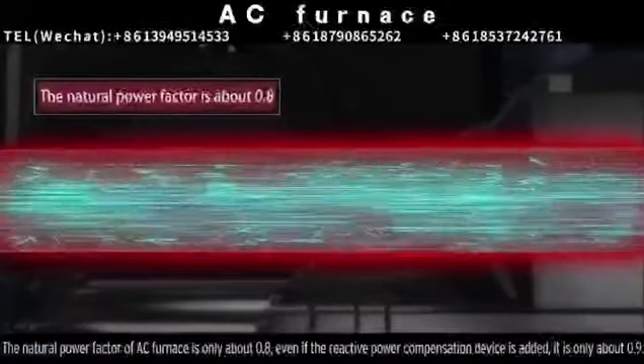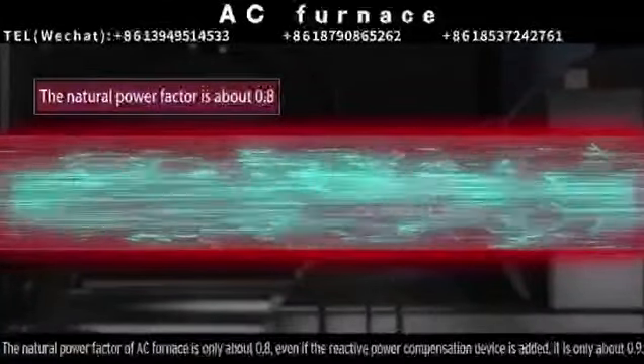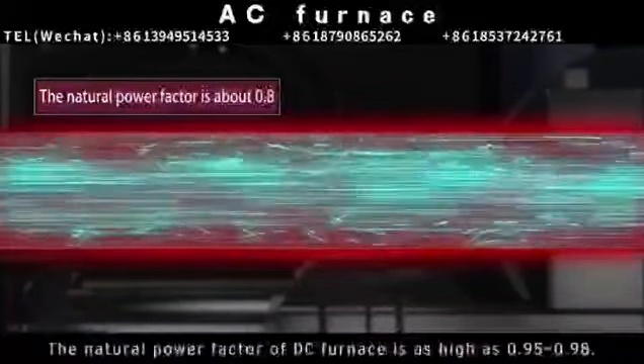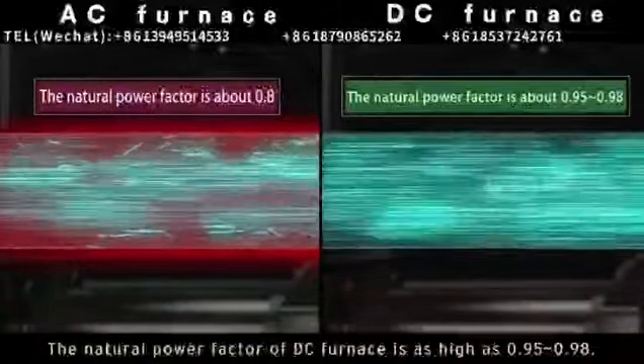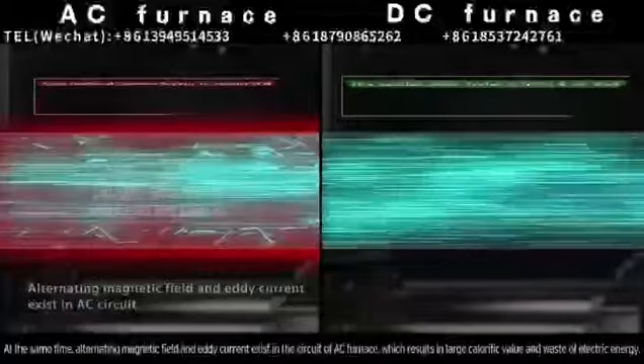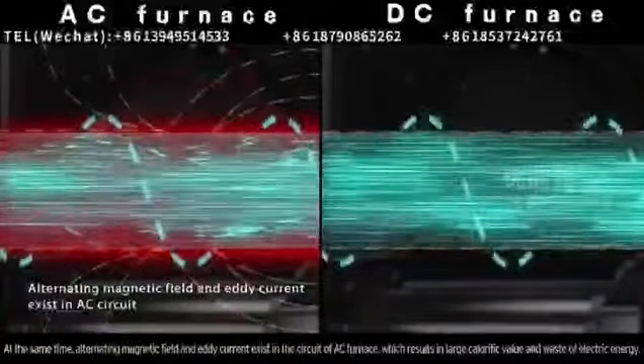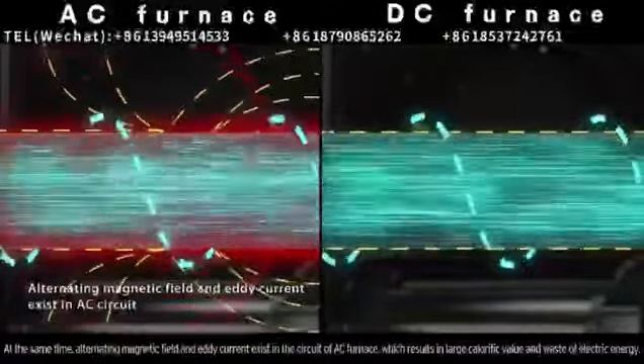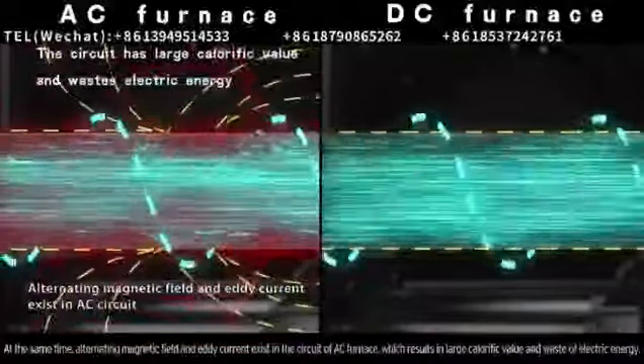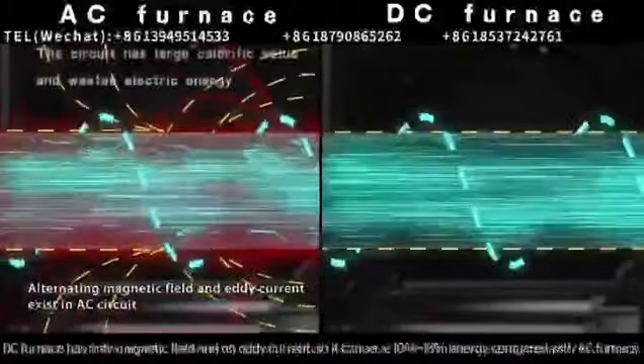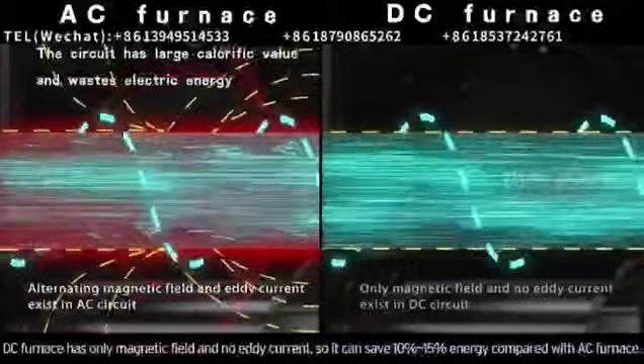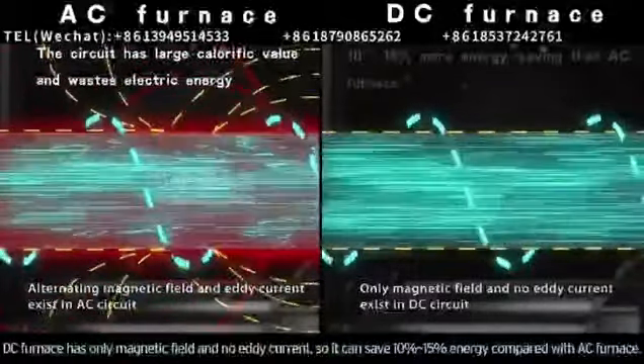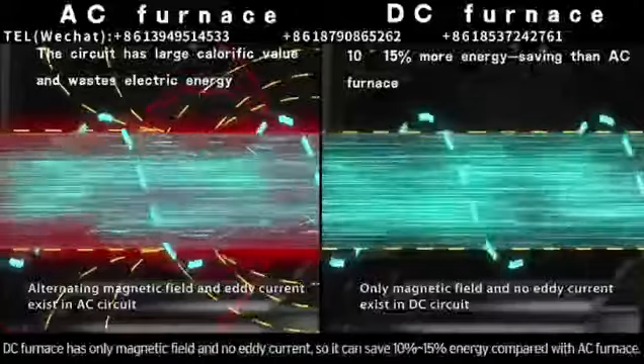The natural power factor of AC furnace is only about 0.8. Even if a reactive power compensation device is added, it is only about 0.9. The natural power factor of DC furnace is as high as 0.95 to 0.98. At the same time, alternating magnetic field and eddy current exist in the circuit of AC furnace, which results in large calorific value and waste of electric energy. DC furnace has only magnetic field and no eddy current, so it can save 10% to 15% energy compared with AC furnace.